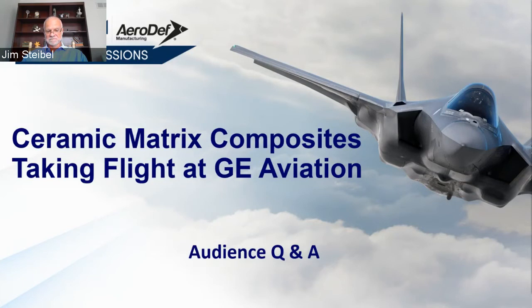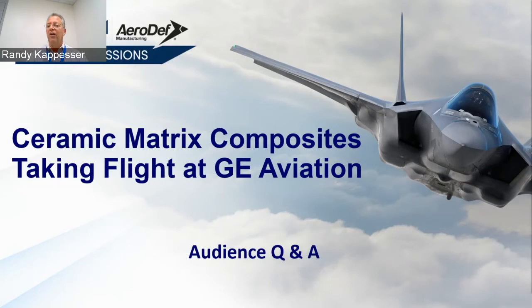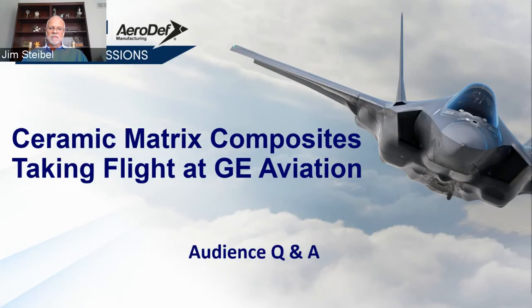Okay, I'm going to skip over one that's along the lines of challenges for tooling. We've kind of talked that some. Okay. What joining approaches are you using with CMCs? So in our case, the molten silicon infiltration process can be thought of as an inherent joining method because you are converting carbon to silicon and creating bonds while you're creating the part. So joining for us is really co-processing. It's not really your traditional bonding. You're not bringing in a secondary bonding agent, and it's not necessary. And co-processing allows us to make very large, complex, multi-piece assemblies.